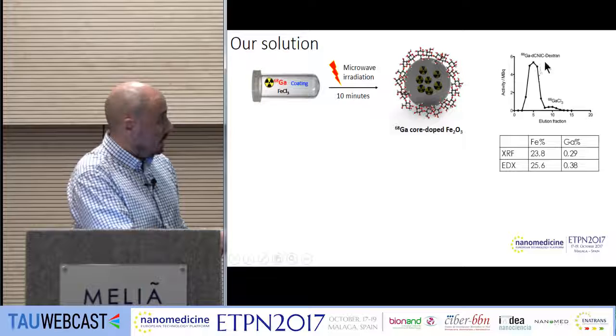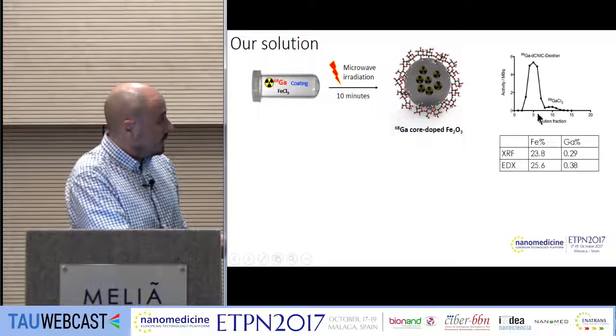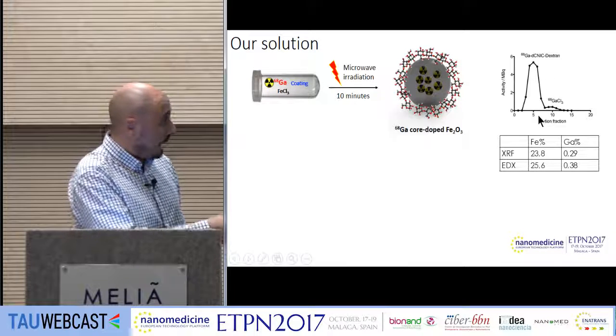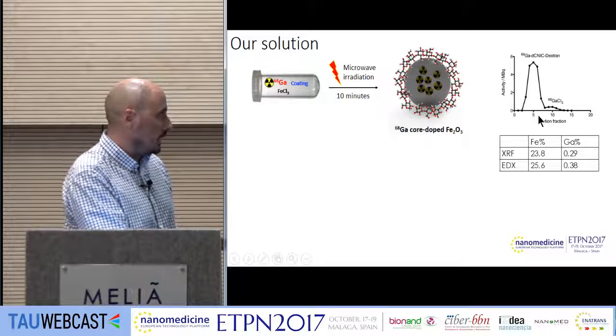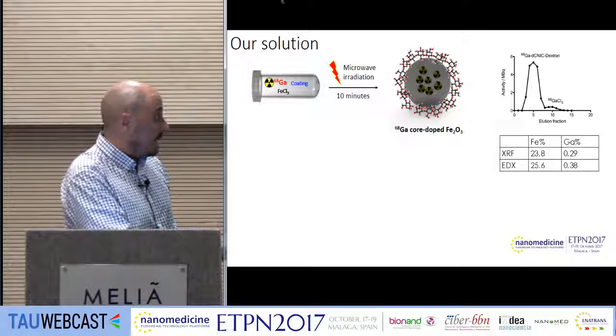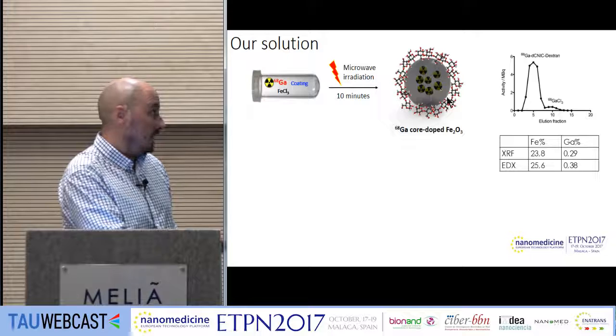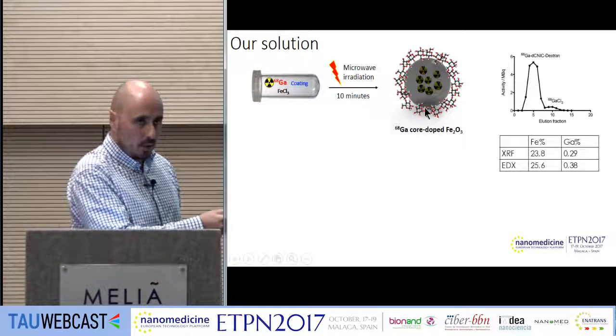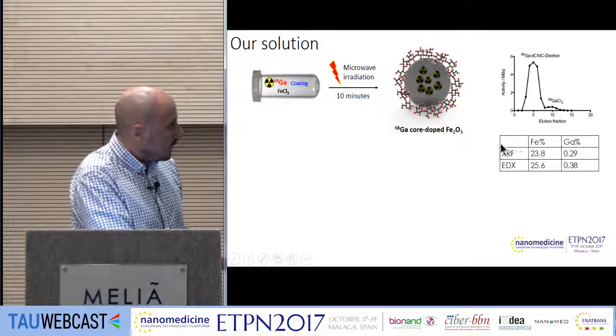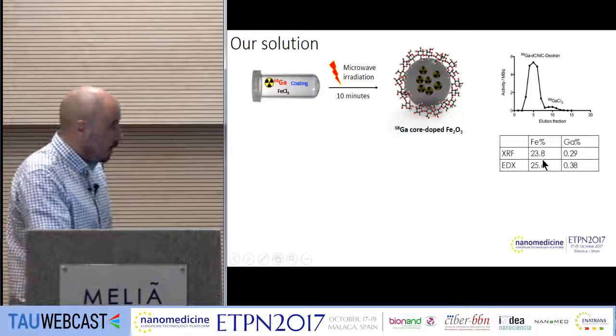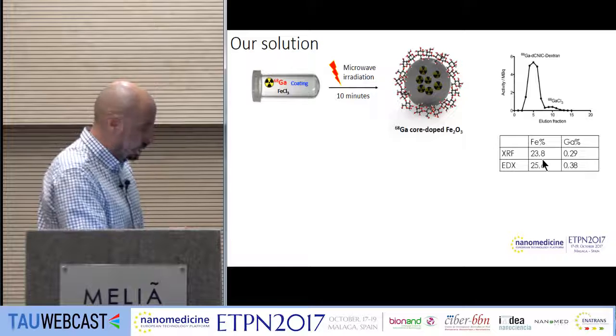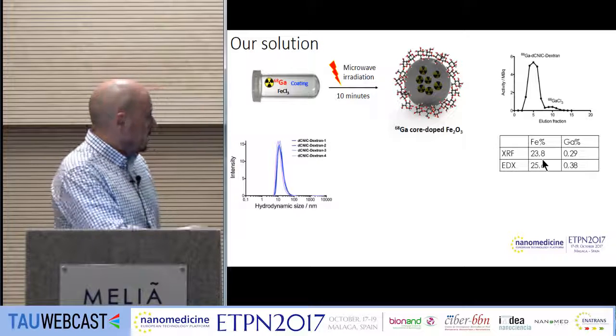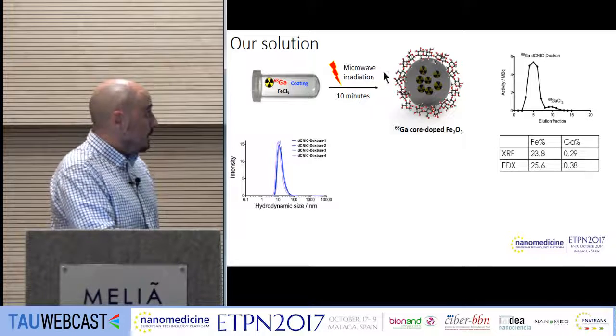This is the radioactive signal due to the nanoparticle, and this due to the small amount of gallium that has not been incorporated. We characterize that, in fact, the gallium is in the core, in the crystal structure of the iron oxide nanoparticles, by different techniques. For example, here, X-ray fluorescence and EDX nicely agree on the percentage of iron and gallium in the nanoparticles. Another advantage of this method is the reproducibility.